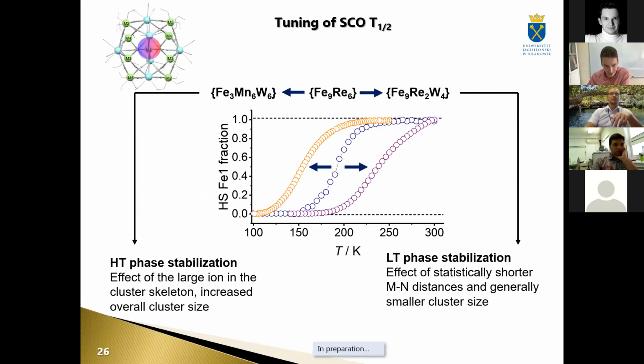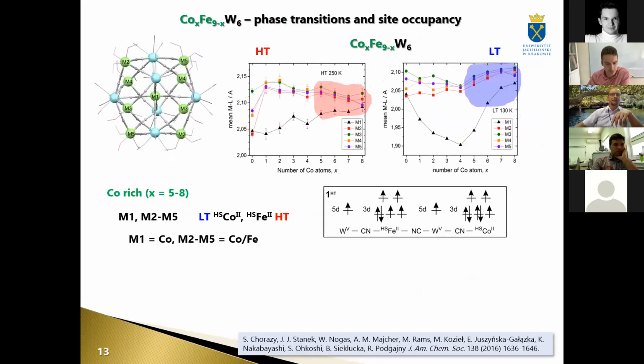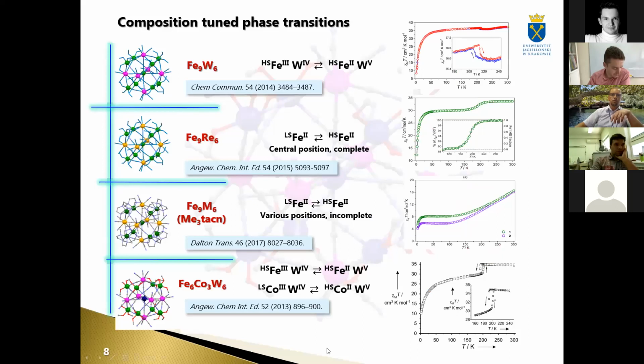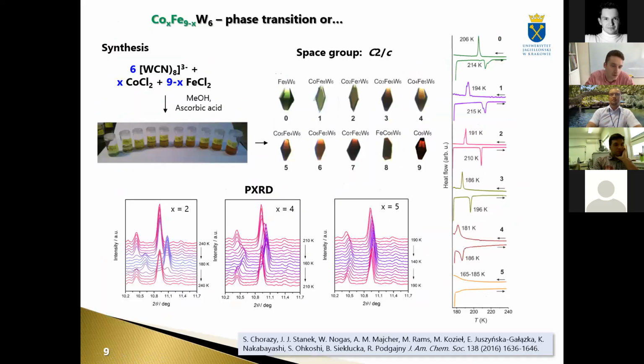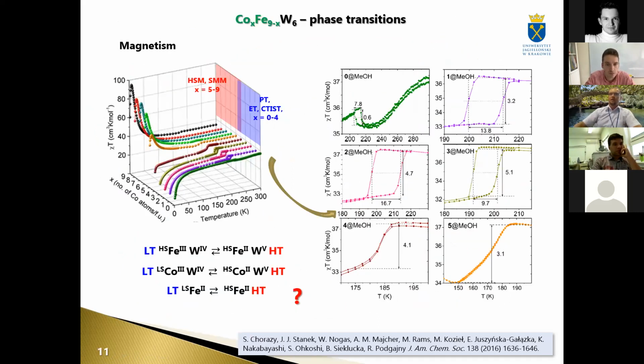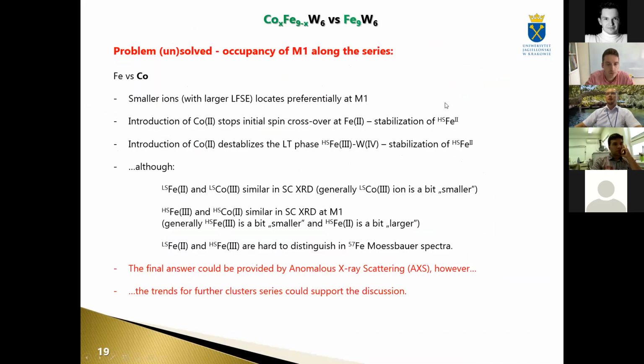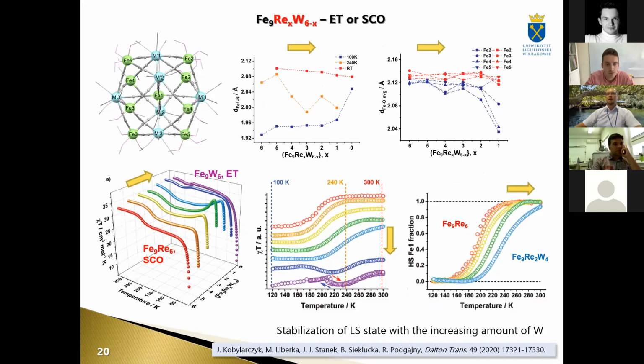Okay, knowing that, because we started from this composition, I think it was tungsten 6. Yes, this one. Iron 6, cobalt 3, and tungsten 6. So we started with that one. There was the first leading paper, and we have seen something which was quite new at that time. And now, before we do any other characterization for these compounds, we perform the scanning microscopy measurements using EDS facility. So no, excuse me, this is not the question how to control, but how to organize the synthesis to obtain exactly the exact composition.